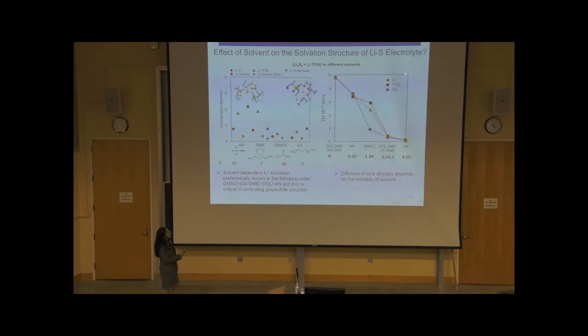And when we looked at the diffusion coefficient of lithium, TFSI, and polysulfide species in these different solvents, we found that acetonitrile has the fastest mobility of ions, and that's mainly because of its low viscosity, followed by DMSO and then this DOL-DME mixture. So you would notice that the viscosity of DMSO is actually higher than this DOL-DME mixture, but the dynamics is still faster, and the reason is that DMSO is a very good solvent. It can easily dissociate lithium from the anions, so they are well separated in the solution and free to move. They're more free to move as compared to DOL-DME, and that's why the diffusion coefficient of all these three species is much different compared to DOL-DME, where all the species are moving together in the solution.